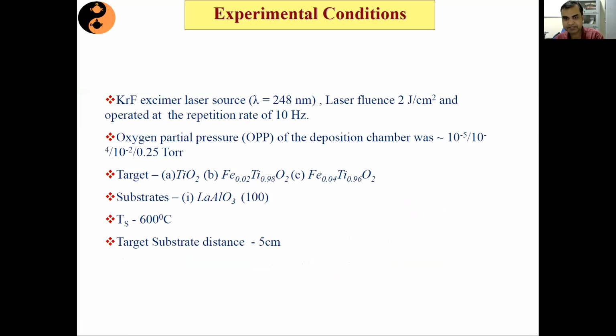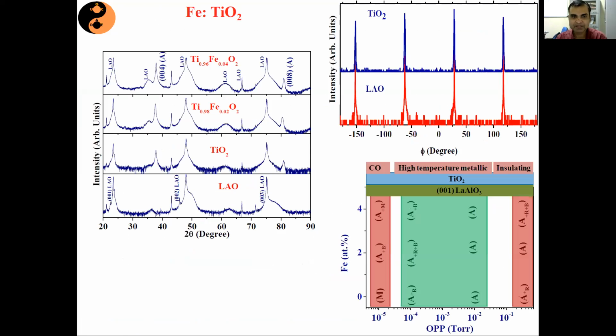So we prepared its thin film by having undoped TiO2, then 2% iron doped TiO2, or 4%, by varying the iron concentration in this system. And you can see that the system was single phase in nature and it had an epitaxial behavior, as can be seen here. So this iron doped TiO2 was single phase in nature.